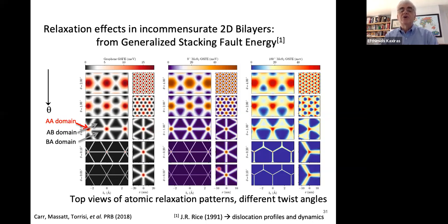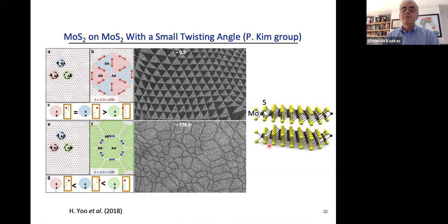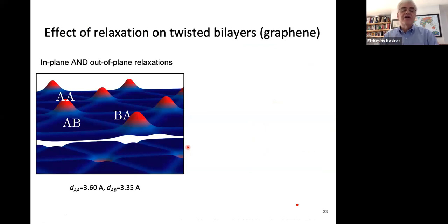Similar effects are shown here in twisted bilayer molybdenum disulfide. This can be stacked in two different ways. That's why you see two different patterns. And this nicely explains experimental measurements. So this is the molybdenum disulfide crystal in perspective, two different types of atoms, two different possible stackings. This is the stacking that makes it look like graphene. This is the different stacking with very different patterns of domain walls and very close to what we predict by our theoretical analysis.